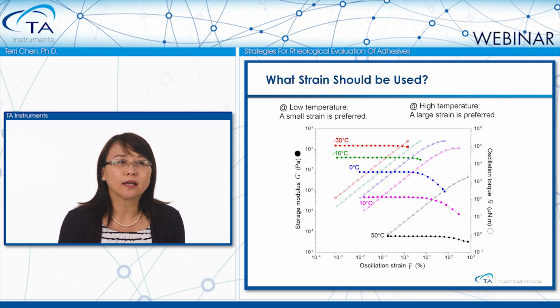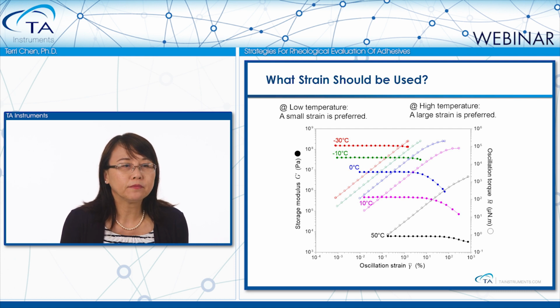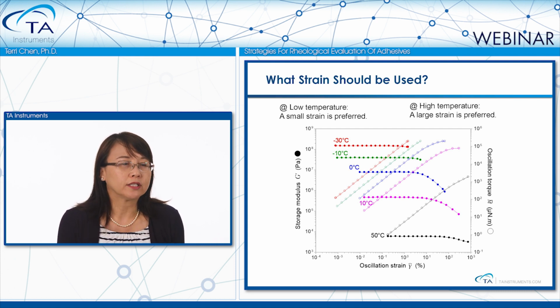So how do we decide what strain to use for a certain sample testing? This figure shows a series of strain sweep tests at different temperatures from below glass transition until above glass transition. First, let's look at the red curves, which is the strain sweep at minus 30 degrees C. As we can see, below glass transition, sample modulus is high, and at a strain of 1%, this measurement maxes out the instrument torque. It means that we are not able to go to any strain higher than 1 to 2%.